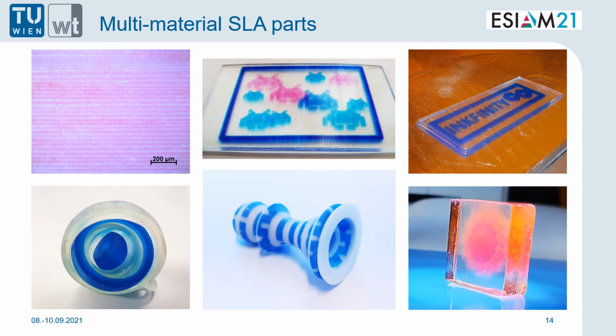Also crucial for future applications is the compatibility of ink and resin, which has been tested for various combinations during these first studies. You can see here a set of multicolored parts printed with this new hybrid system. Printed were glass-like amorphous resins, tough resins, which needed over 70 degrees C to be printed, filled resins, and composites like this artificial ivory structure you can see here in the middle. Using multiple printheads in a row, it is even possible to include multiple colors in one part.